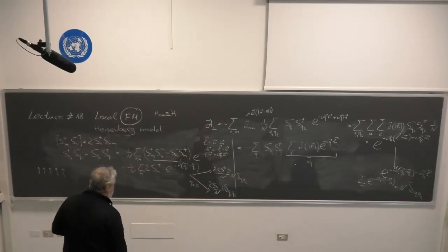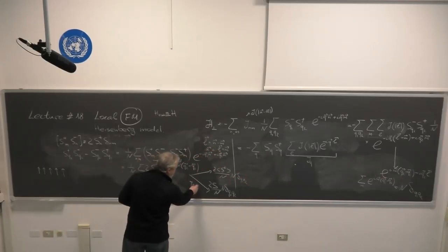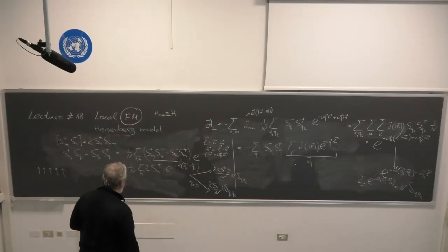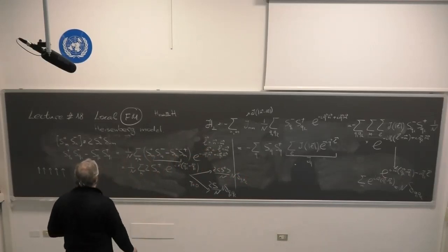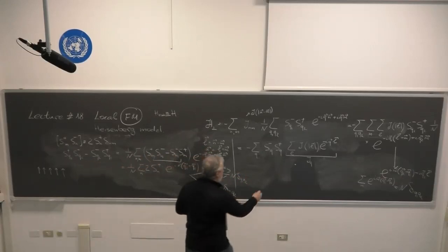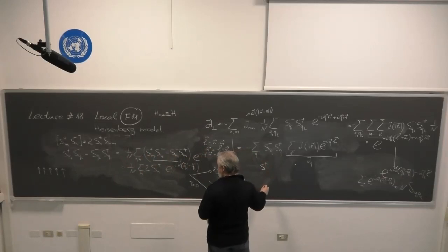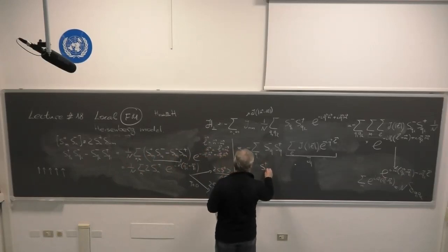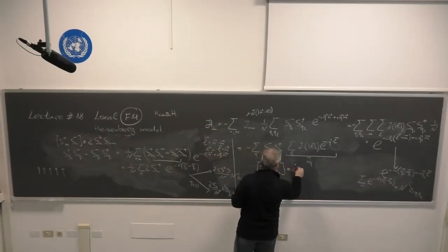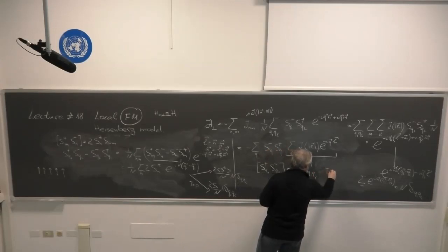If, however, I'm not at zero temperature, I can do a sort of mean field treatment and replace it by 2 times the average of S^z, which will be the average magnetization divided by N, times the delta symbol q1, q2. So suppose I'm at very, very low temperature. Therefore, what I see here is that the commutation relation of S plus q1 and S minus q2 is equal to 2S delta q1 q2. Again, provided that I am at zero temperature.